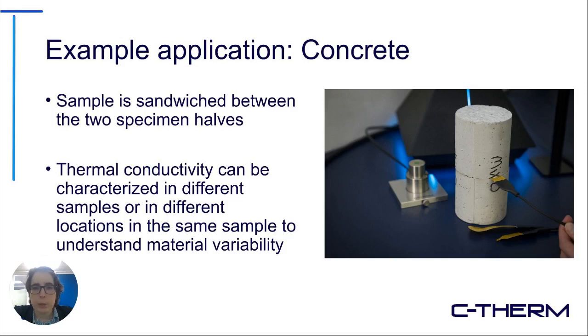So, looking at an example with concrete, in this case, we basically took a single sample from the client and cut it in half, and then sandwiched that material, each half of the cylinder, around the sensor to run the testing. Thermal conductivity in this way can be characterized across many different samples or in different locations with the same sample to help you understand the material's variability.